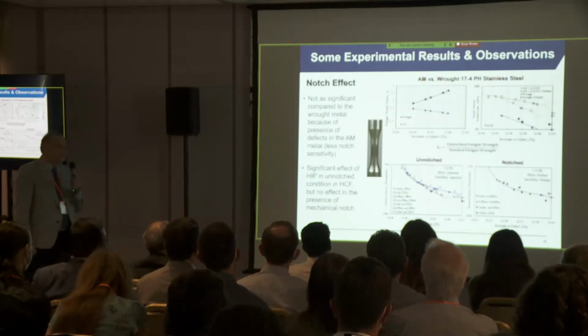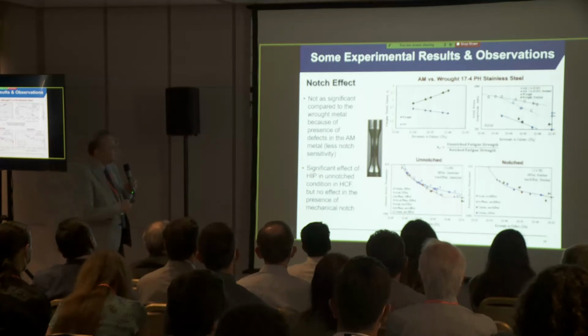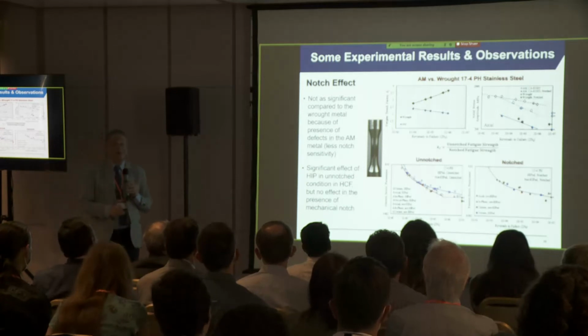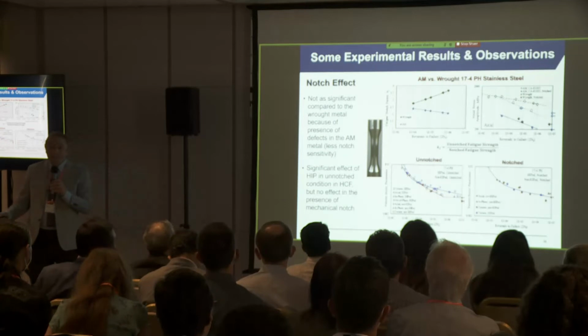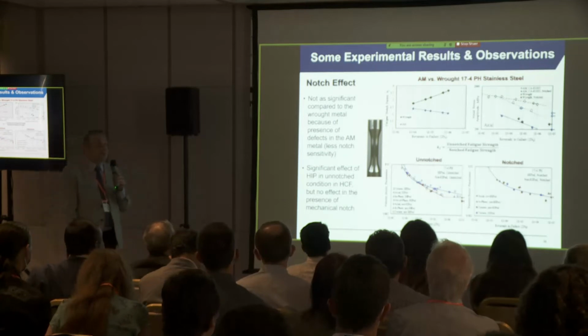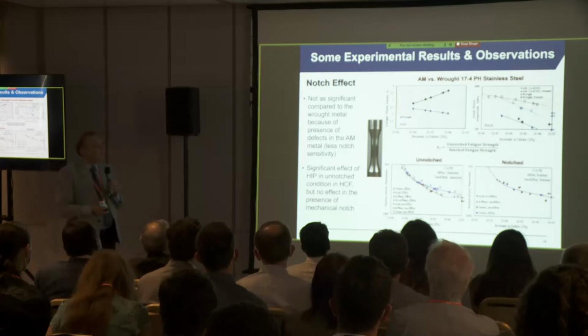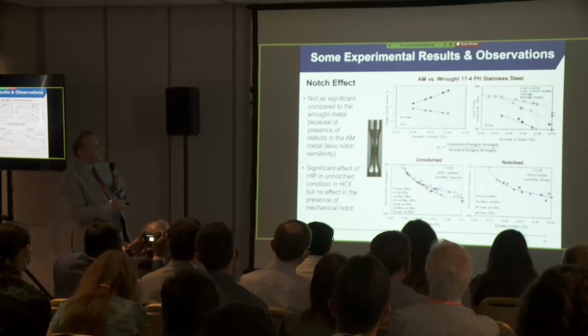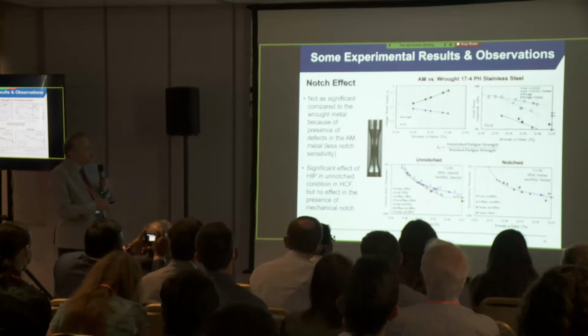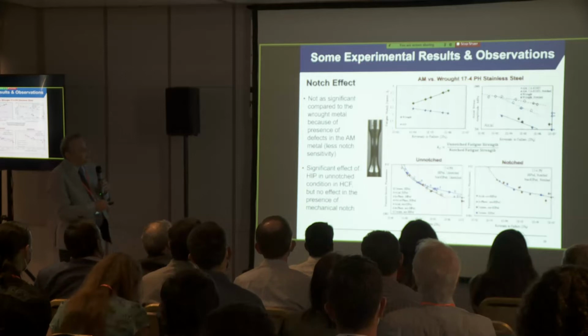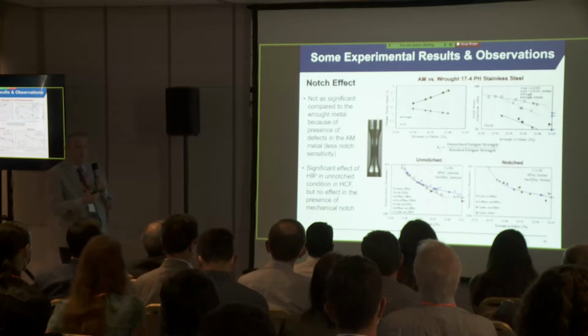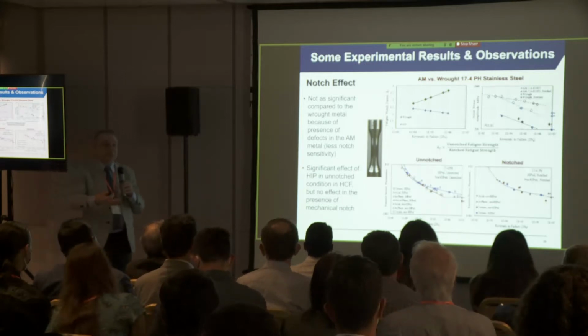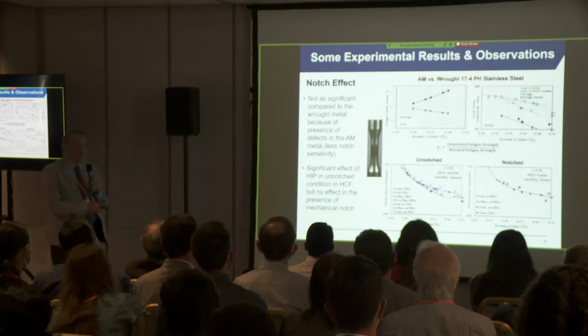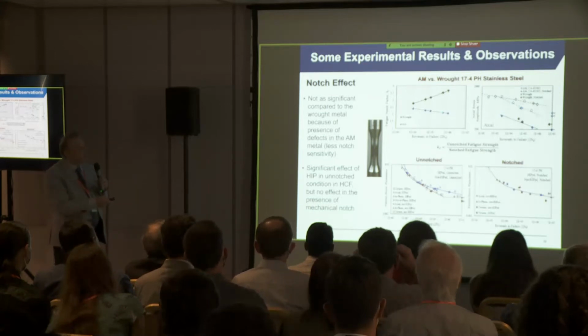Okay, notch effect is very important, but the notch effect is different in additive manufacturing compared to wrought metals. And the reason is that when we have a notch in a component, in the wrought metal, what drives fatigue failure is the stress concentration of the notch. So if we look at fatigue notch factor, this is for the wrought metal. It increases with life. In other words, there is more notch sensitivity with the notch. Whereas for additive manufacturing, notch sensitivity actually decreases.